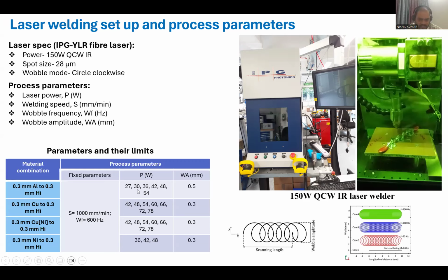So based on some initial trials, I have randomized the welding power. I have only changed the welding power and fixed the other parameters, because if I change everything, then I will end up doing 1,000 trials or 1 lakh trials. So I did some initial trials first, and I identified which parameter is significant and which is not significant. I fixed those parameters which are not significant. I have only varied those parameters which are highly significant and had the most significant effect. So that's why I fixed the welding speed and wobble frequency at certain values.